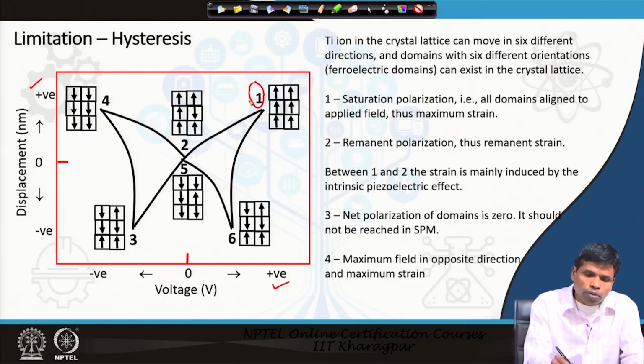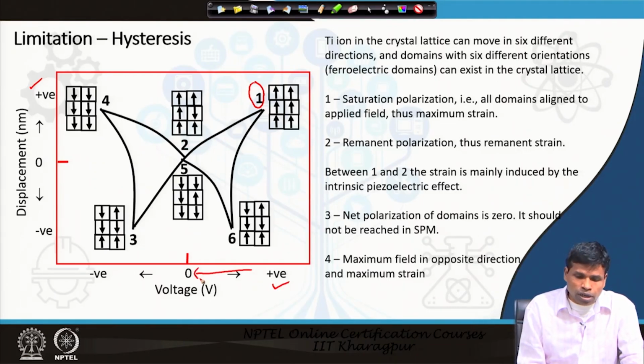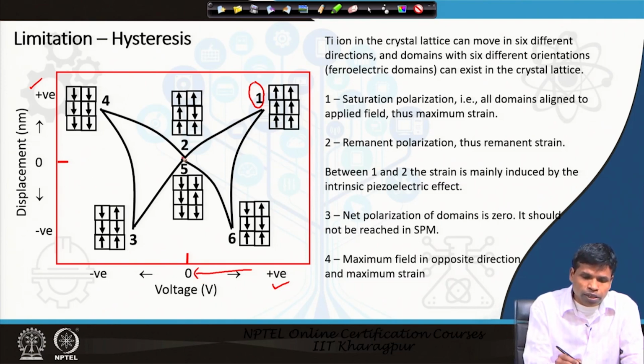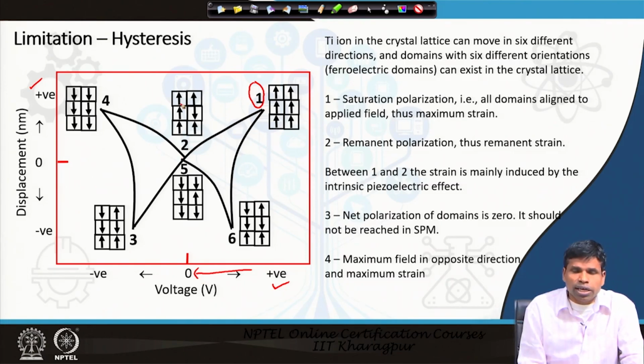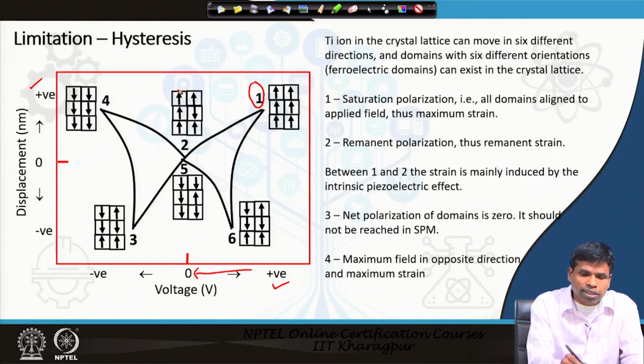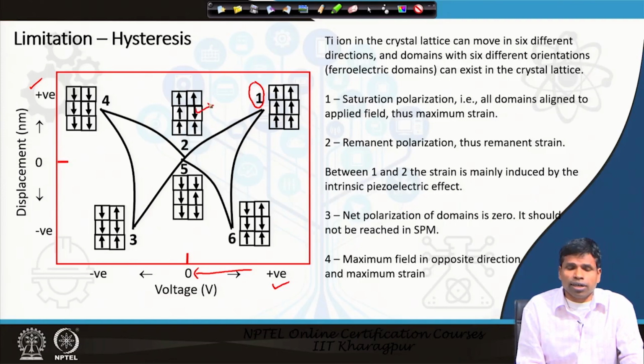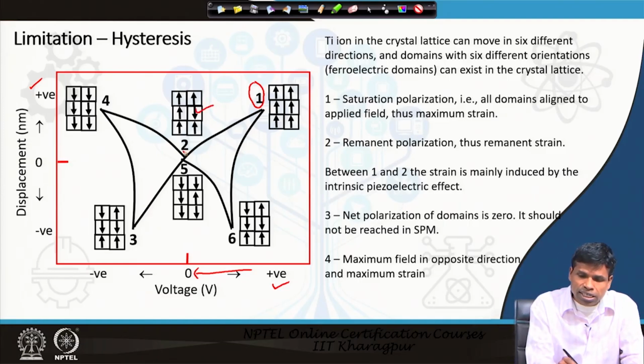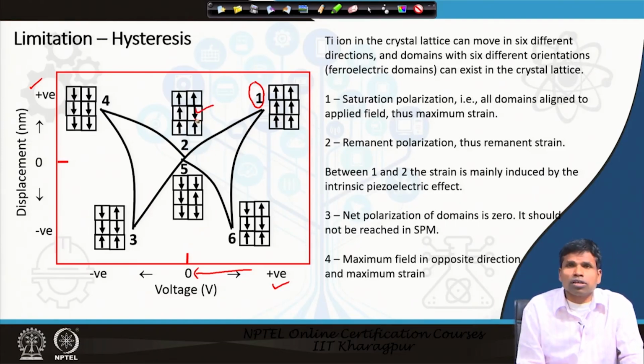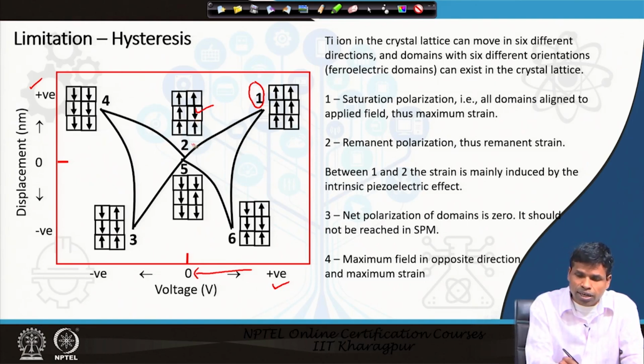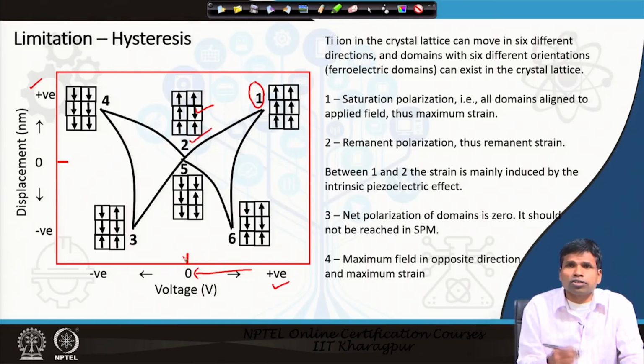And when we go from 1 to 2, by decreasing the field, or when the applied voltage is reduced to 0, then most of these domains again align with the outer field, but there is one domain which is reoriented, and this state is what we call the remnant polarization, thus having remnant strain. So, the remnant strain or remnant polarization is the polarization or strain at 0 applied voltage.